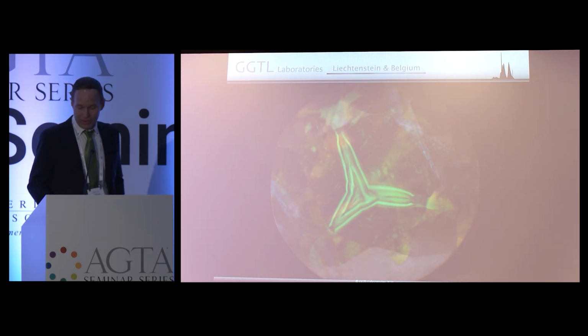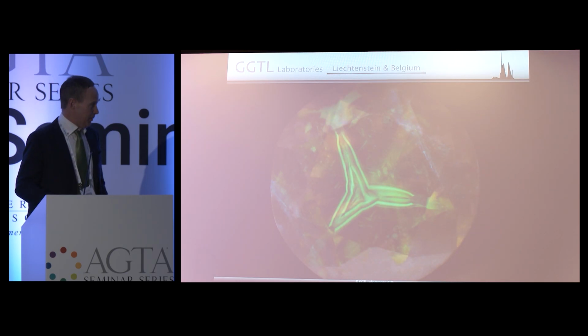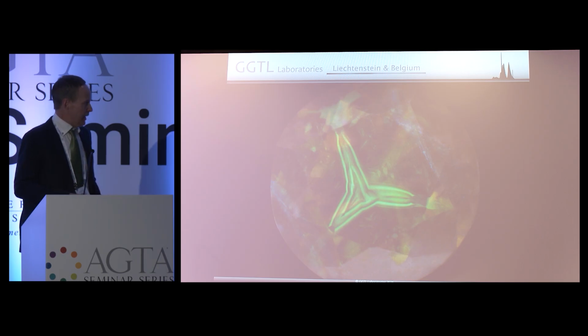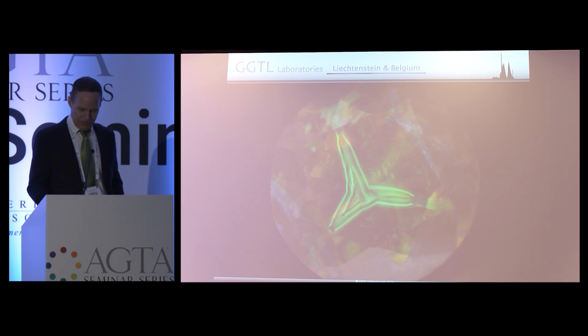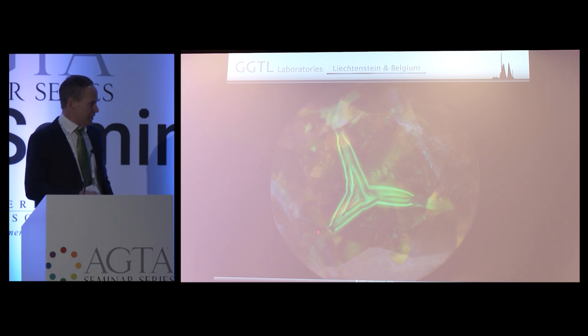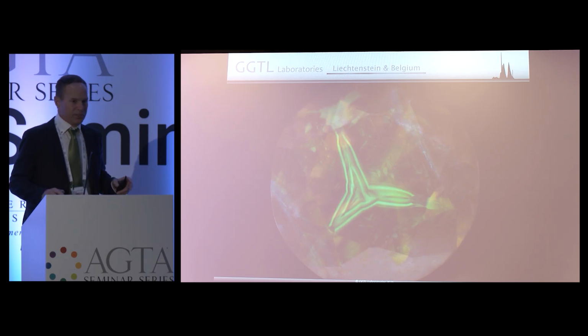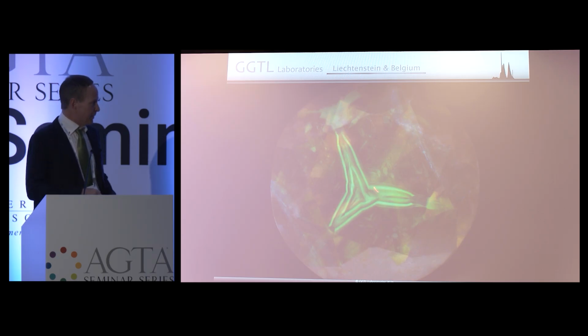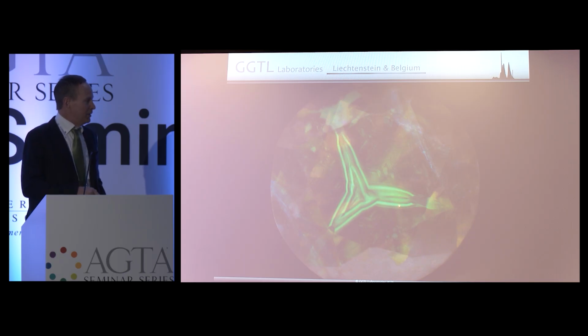This is the type Ib. It's actually just a single nitrogen containing yellow, vivid yellow diamond. This is one of the most common kinds of patterns that we see. But rarely is it so nicely developed that you see this beautiful kind of Mercedes star pattern as we see it here. This is the same defect that causes this green fluorescence as what we've seen in the Zimbabwean stone before. Same thing. And here it develops these beautiful sectors again from mixed growth.